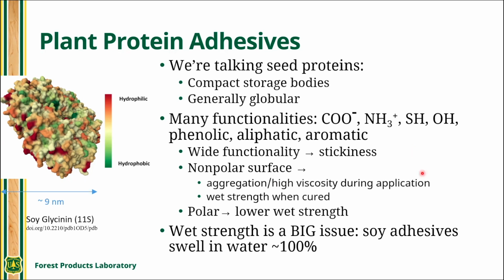So this nonpolar surface leads to viscosity issues, but I also believe that nonpolar surface gives you wet strength in the cured state. So we'll talk more about that later. And polar draws water in, and polar bonds are weakened by water, so we don't want these polar interactions to dominate the adhesive. Wet strength is a big issue with these.